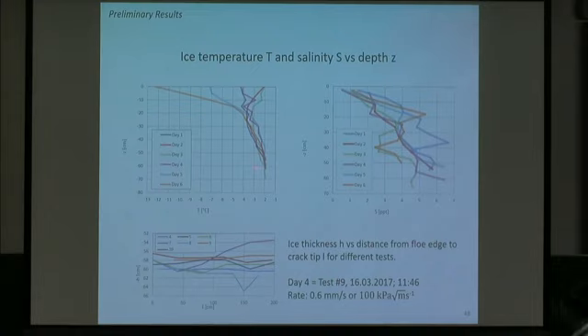Then if we go and look a little bit at one test here, that could be some thick and thin sections. You see this year, and it was actually the same in 2016, the temperature in the ice was relatively warm. We can say that we have an average here of around maybe minus 4 or so. The jack was located here at this surface at this depth, 30 centimeter below. And if you look at this test number 9, we had a rate there of 0.6 millimeter per second, corresponding to 100 kPa square root of meter per second. We can look a little bit more into that.